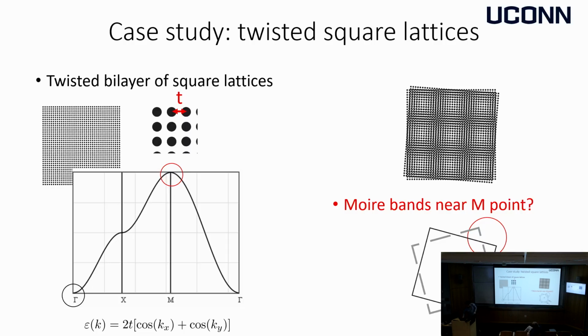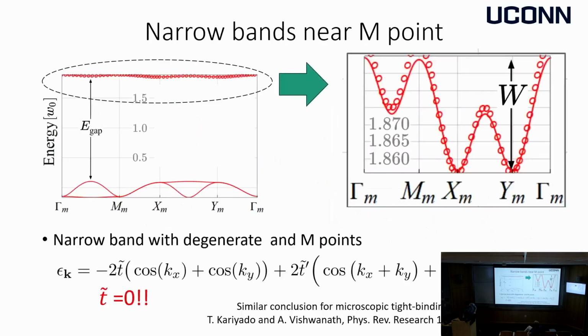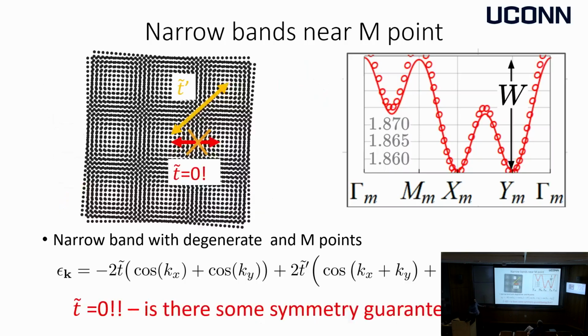And let me go through. So what you see is the following. You indeed form a flat band at low twist angles. But if you analyze, that flat band has no topology. There's nothing too fancy going on. But if you look at the tight binding description of that flat band, you find that the nearest neighbor hopping on the moire lattice is exactly 0.